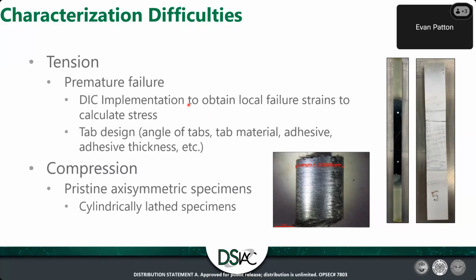So we needed to implement a strategy to get around that piano string, which led to localized cracking within the specimen itself. And to do that, we implemented DIC to obtain a local failure strain to back calculate a theoretical failure stress, because that's what we're ultimately looking for. And then the compression specimens, simply put, we needed pristine axisymmetric specimens. Commonly prismatic rectangular specimens are used, but in order to manufacture those, you need 3 different planes of symmetry, both the top, bottom, and the sides, all 4 sides. So to get around that, we figured what better geometry to choose than a cylinder, because you only have one face to really worry about.